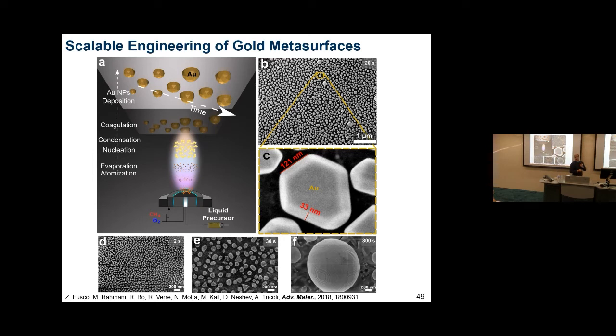Finally, going a bit away from chemoresistive sensors, we are also working this year on other types of detectors. This one I want to show you is an optical type of sensor. We found a method to develop very well-controlled gold nanoislands on a surface in a very short time. We use the same flame, we deposit it on a substrate, but because gold has a much lower sintering temperature, instead of making this fluffy thing, we make islands.